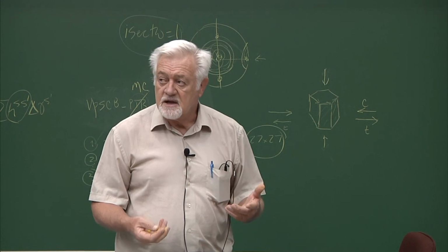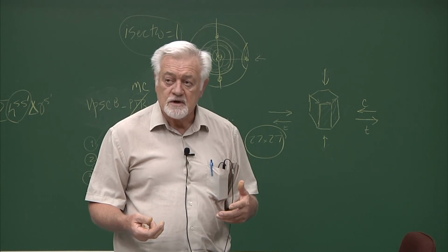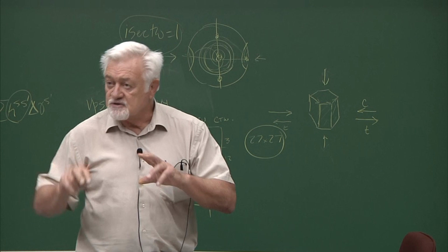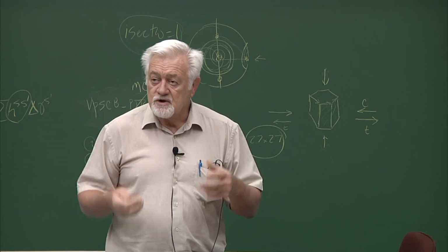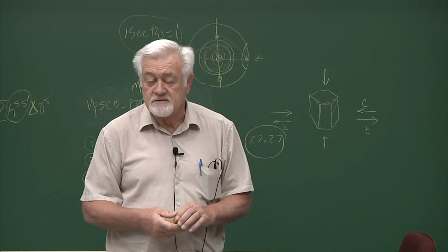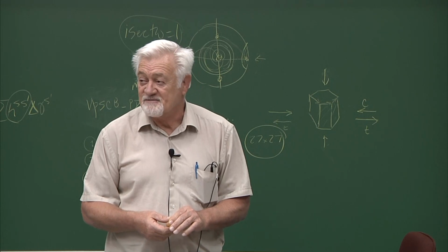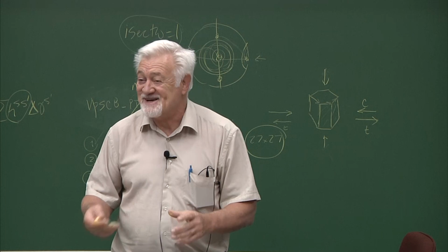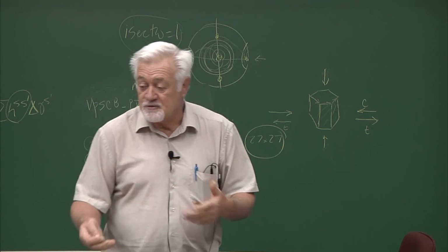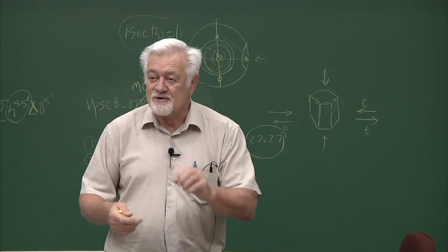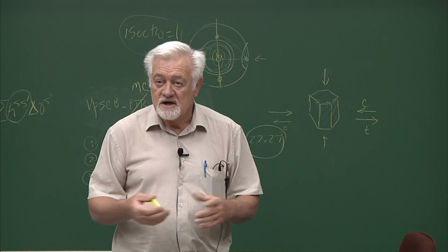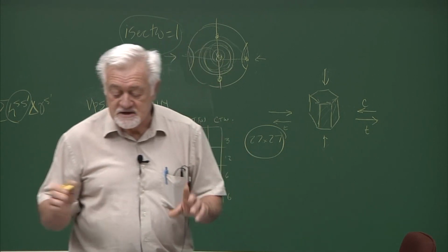But as you can see, it is a complicated interplay between the modes that you activate, and when you throw twinning into the equation, things get even more complicated, because now, as you are deforming, your texture is changing in substantial ways. So all that interplay really gets very complicated, and I always say that sometimes I am marveled by the fact that we can predict anything, because the real material looks very messy, and with these simple models, you can predict things. So I mean, you can predict up to a point. There is a lot of micron-size scale things that you cannot predict with this model, but texture and stress-strain response come out fairly reasonable. So sometimes I'm surprised that that's the case.